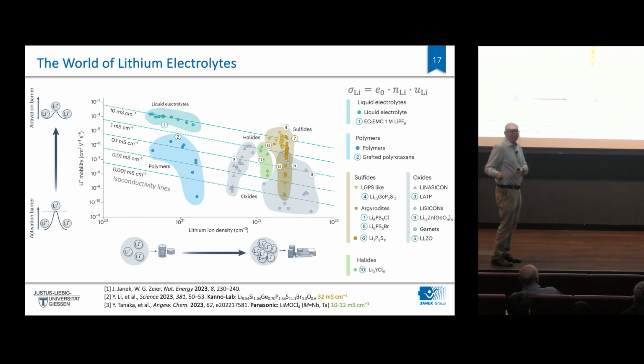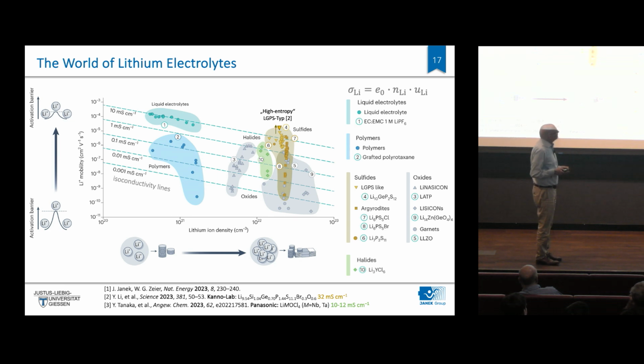As a side comment, if we switch to sodium ion technology, that is not anymore an issue, because sodium ions are so cheap. So that's why going solid with sodium ion batteries has also a cost advantage. And the good thing, of course, is that inorganic chemists are restless in making better electrolytes. Today, there are materials for lithium-ion electrolytes that even approach 40 millisiemens per centimeter, and for sodium, we already have electrolytes that approach more than 100 millisiemens per centimeter. Then you have a pellet of a solid electrolyte that has only a resistance of 1 ohm or something. So conductivity is not anymore a barrier or a limit for solid-state batteries. We have excellent solid electrolytes.